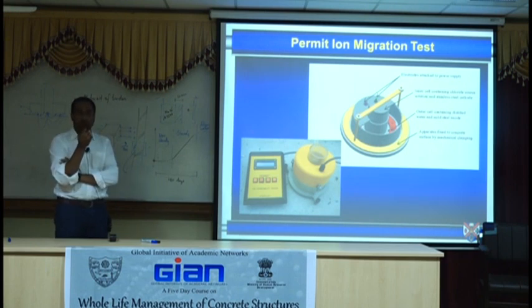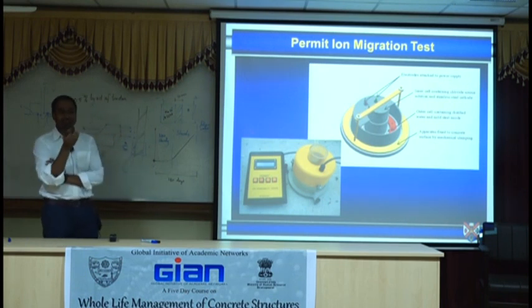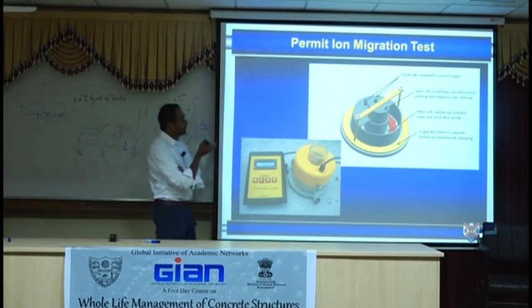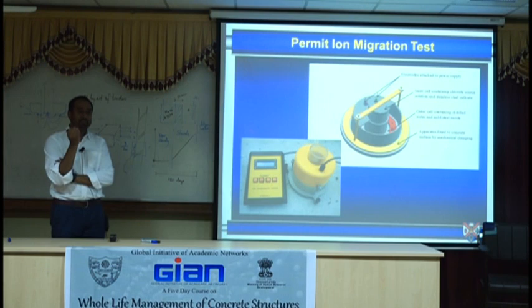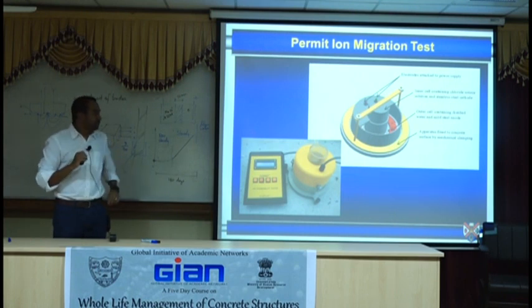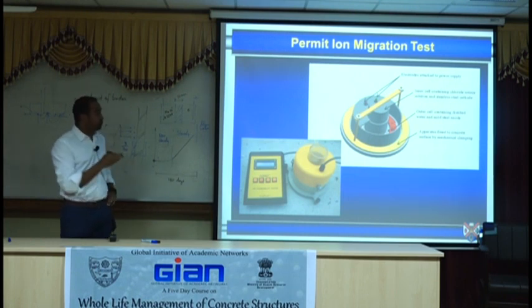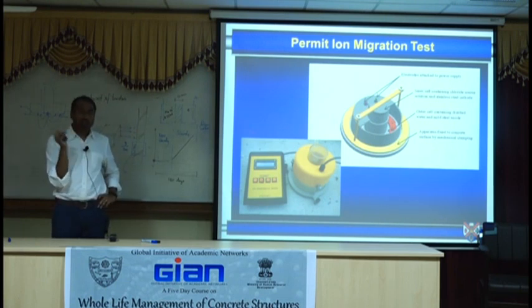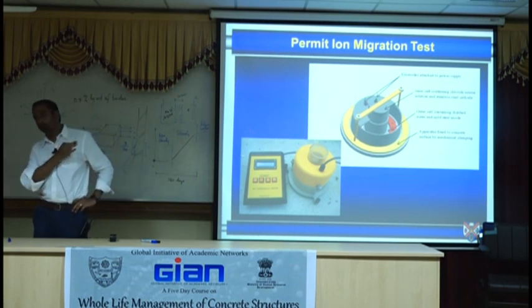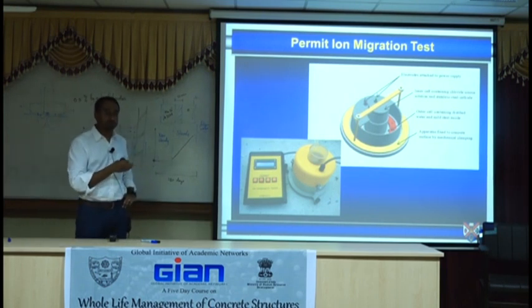But it's not without limitations, okay? All of these tests have limitations. Can you tell me the first limitation of that test? What is it pushing into concrete? It's pushing chlorides into concrete. The very thing that you're trying to avoid. But the amount of chlorides that it's pushing in is so small that it's nominal, that doesn't really affect your steel that much. But it still does push chlorides in. So if you're going to do that for testing any pre-stressed tendon-based concrete structures, I would be very cautious. You should be testing areas where you don't have any of those major structural parts.